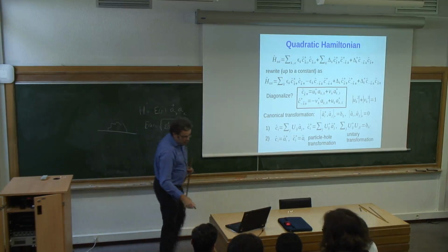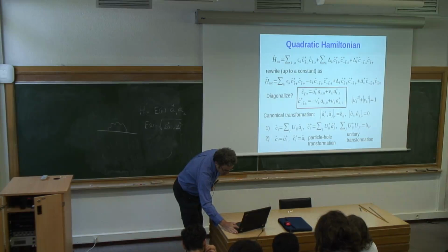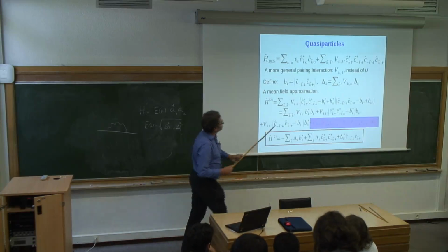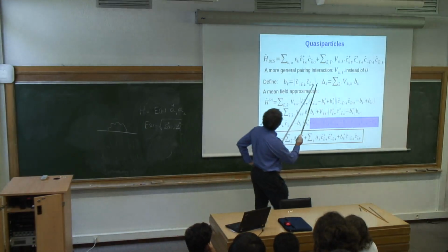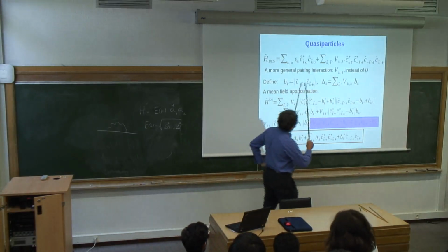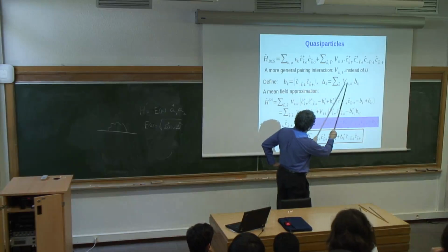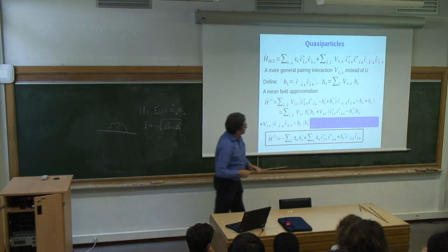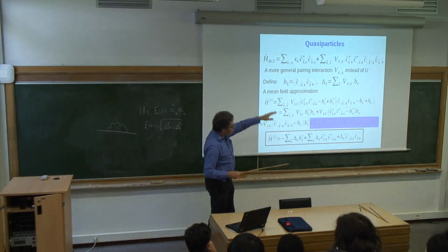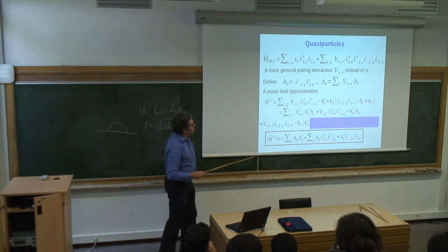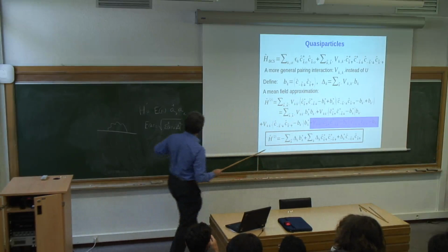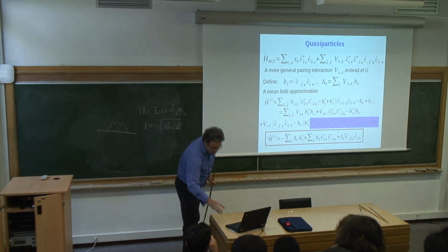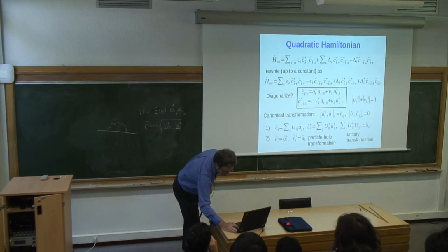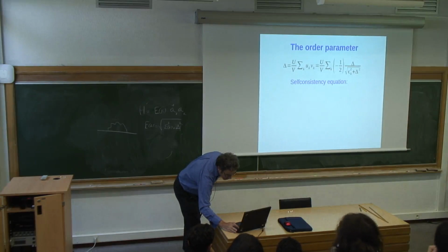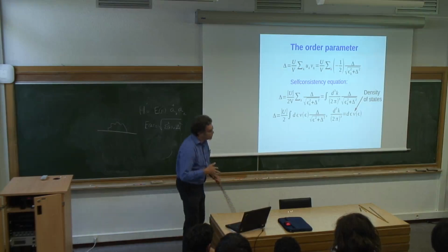Right. So here, in a stealth way, I already introduced the superconducting order parameter, which turns out to be defined through pair creation operator expectation values in this way, by multiplying them by the pairing interaction. And so what can be shown by doing this calculation is that it is this value that will correspond to the gap that opens up in the particle spectrum at the Fermi level. Sorry for the missing slide.